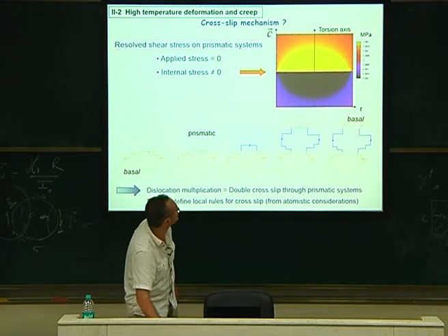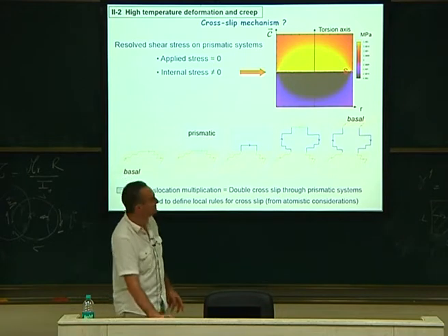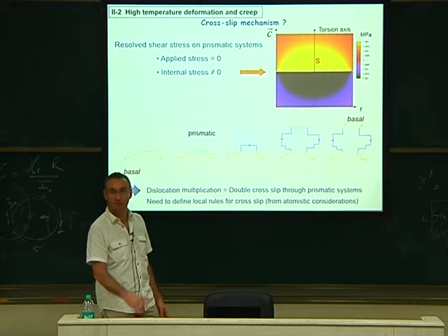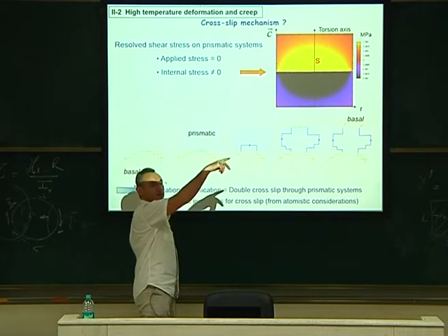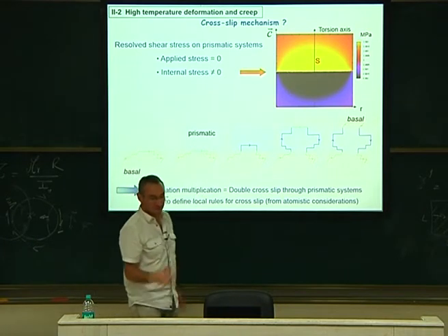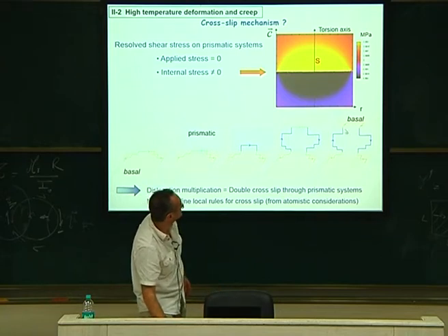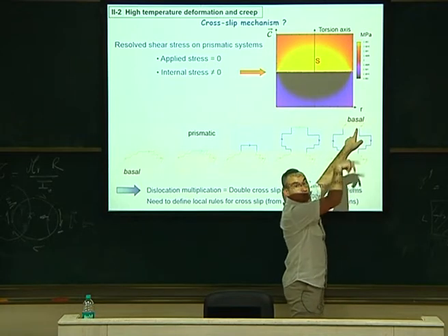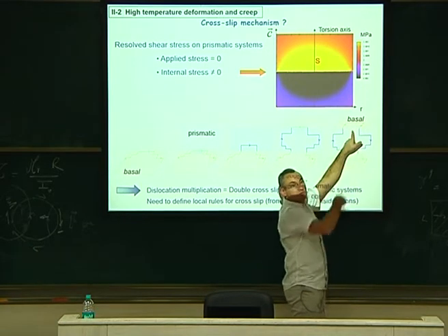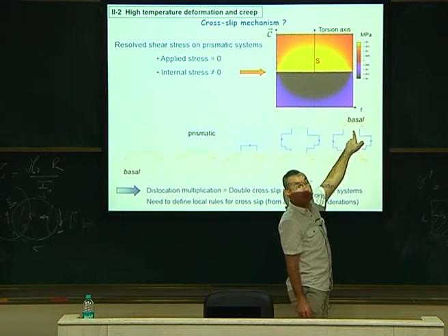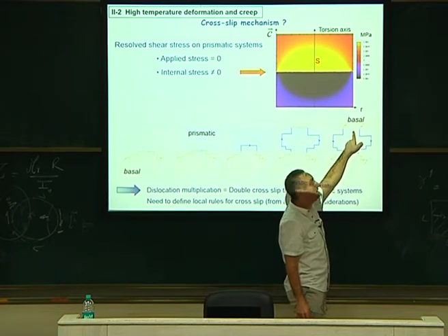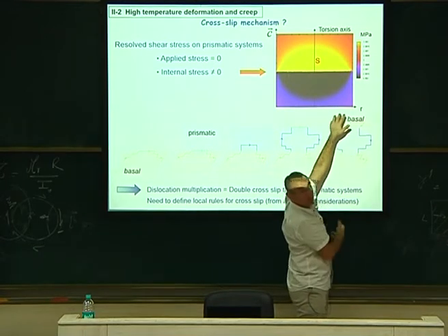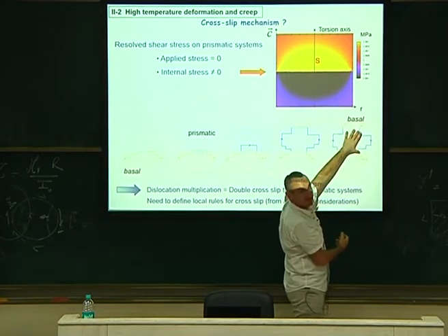So actually, you have a small PowerPoint animation here. The screw is coming, cross-slips, and goes on. So this is what occurs. We have glide, cross-slip, and glide. The good thing out of it is that when it cross-slips here and cross-slips back, this is like a Frank-Read source. So here it will be able to make a new twist at that place typically. The distance at which it will occur is just the ratio of the applied stress and internal stress. This gives you this distance here typically.